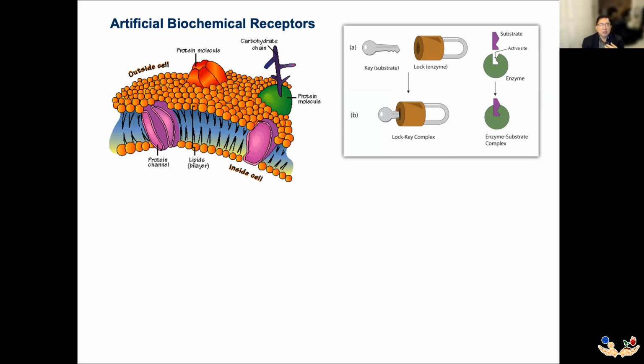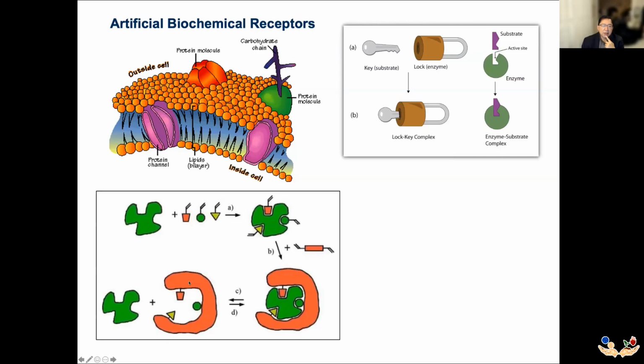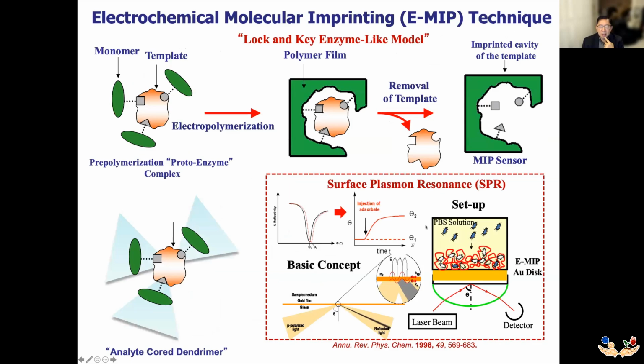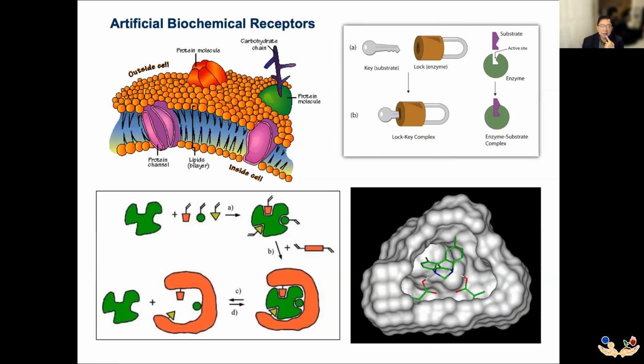Let's say the key is available, which is the substrate or the template, but the lock is not available. So basically, what we have to do is construct a lock around the key. And this involves chemistry where the original template is complexed with monomers that can be cross-linked or polymerized, resulting in a cavity that's very specific for that original molecular template. We call this molecularly imprinted polymers. In this case, it mimics that of an enzyme-substrate complex, where the cavity is very specific for that particular substrate or original template.